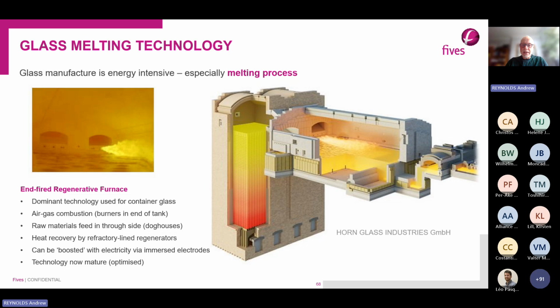The dominant technology used today is what we call end-fired regenerative furnaces. You can see here in the picture the melting tank on the right-hand side, and then behind it are these large heat recovery structures. We use an air-gas combustion system, and we preheat the air coming into the burners using these regenerators, as we call them, which are heated by the exhaust gases coming off the process. And you go through a 20-minute cycling system. The regenerator is in two parts. You heat one side of it on one cycle and use the other cycle to preheat, and then vice versa on an exchange. The raw materials are fed into the side of the unit.